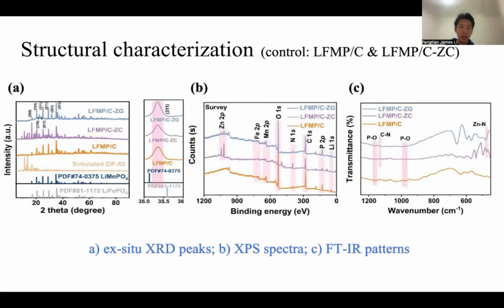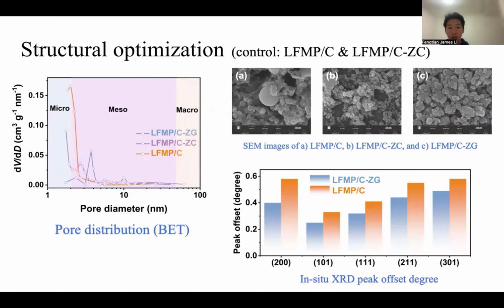Well, so let's look at some results. Here are some characterization tests we did. Basically, it's for checking that this is the material we are synthesizing. And as you can see, the elements and the crystal structure and bonds presented all fit our expectation. Then structural optimization. From the pore distribution analysis, we can already see that ZG material has the most mesopores. From the SEM image, we can see that ZG material has the most uniform surface. So that already validates that this material, compared to the other two we synthesized for control, has a better surface or interfacial chemistry. So it will better enable the transport and electrochemical process.